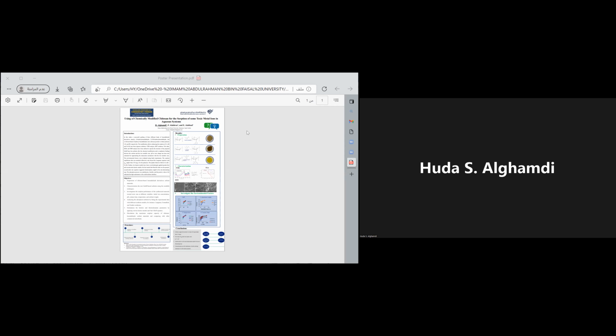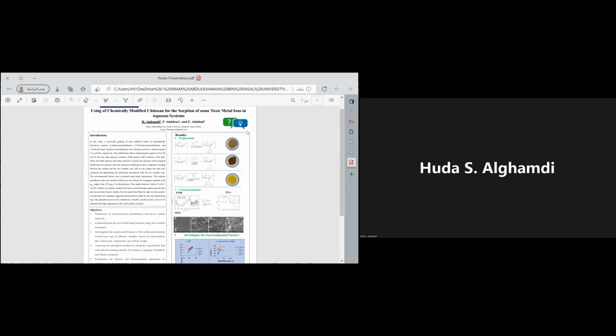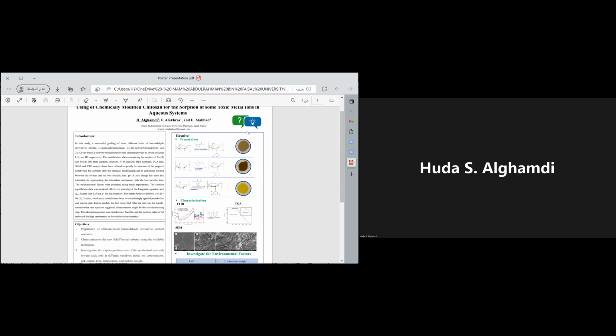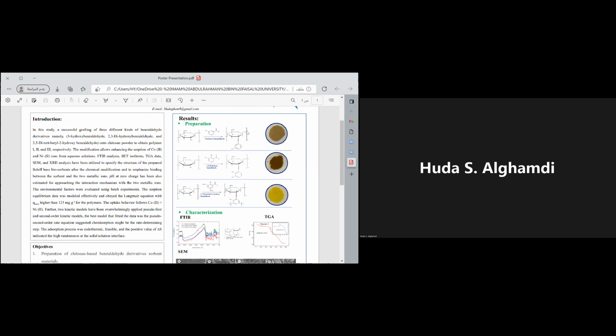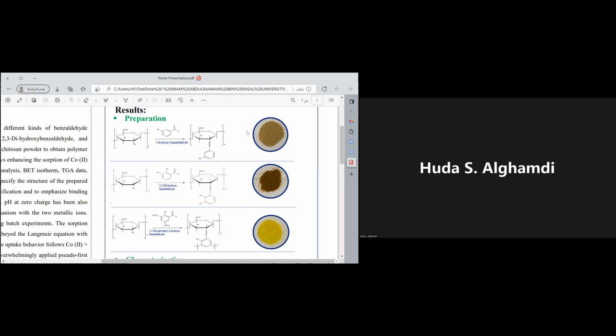This is a study made in the field of water treatment using Chitosan as a biopolymer. So it is an eco-friendly treatment via adsorption process. What we did is that we modified Chitosan chemically using 3 kinds of benzaldehyde to gain more robust polymers to remove the cobalt and nickel ion from water.